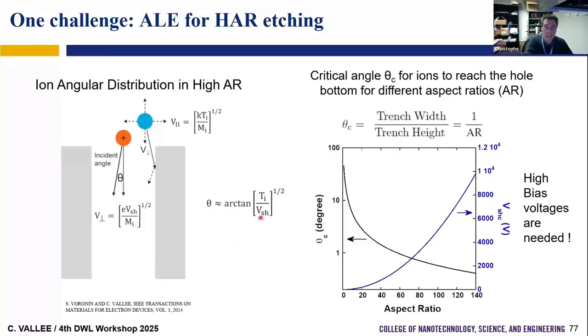And usually you can calculate this angle of dispersion, which corresponds to the ratio between the sheath voltage and the ion thermal energy. The issue is that depending on this angle, you can imagine that most of the ions will never be able to come to the bottom. So if you want to reach the bottom for high aspect ratio, you need to reduce this angle. And so you can try to do the calculation of what should be the maximum angle for a given aspect ratio. And you see that as you increase the aspect ratio, now the ion angular distribution must go from 20 degrees, for example, to less than 1 degree,